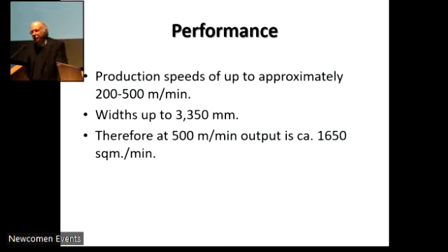Now, modern corrugating plant does not hang around. The production speeds can be up to somewhere between 200 and 500 meters a minute, depending on the nature of the product. Widths can be up to 3.35 meters, which in old money is something like 11 foot. And that width puts a lot of engineering expertise at a premium in terms of ensuring the rigidity of the rollers, that they don't sag, and also making sure that the bearings don't give way at the speeds we're operating at. And at 500 meters a minute for a high-end unit at that sort of width, we're churning out 1,650 square meters of board per minute. And if something goes wrong that impairs the quality, that's an awful lot of duff product awful quick.